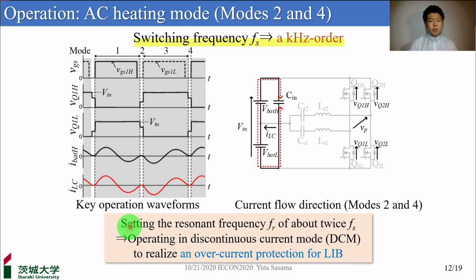In AC heating mode, the resonant frequency FR is set to about twice the switching frequency to operate in the discontinuous current mode, DCM, with a period when the AC current ILC is zero. DCM is known to have constant current characteristics, realizing overcurrent protection for batteries.